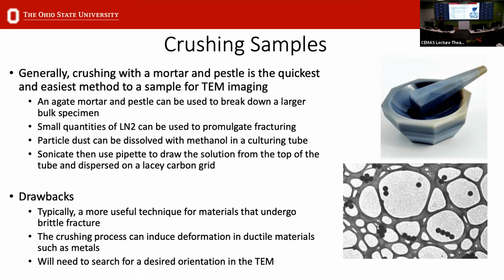So this is good for materials that are brittle, that don't undergo a lot of deformation under the crushing process. So if you were working on a metal that had a high ductility, this probably wouldn't be the best way of preparing your sample. But for ceramics, it can be very useful. In this case, what you would want to do is crush your sample down finely. You could place your powder in a centrifuge tube with methanol, sonicate that, and then use a pipette to grab your solution from the top of your tube, and then disperse that on a lacy carbon grid.